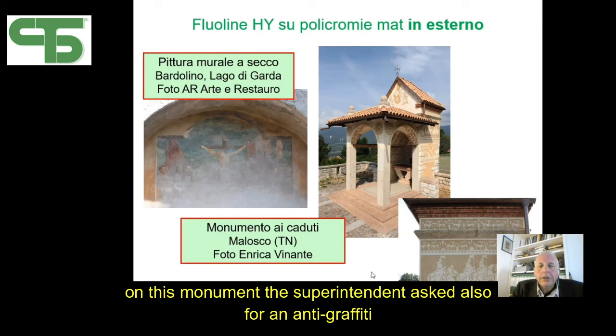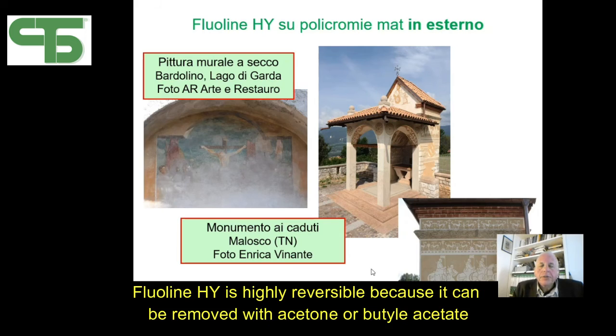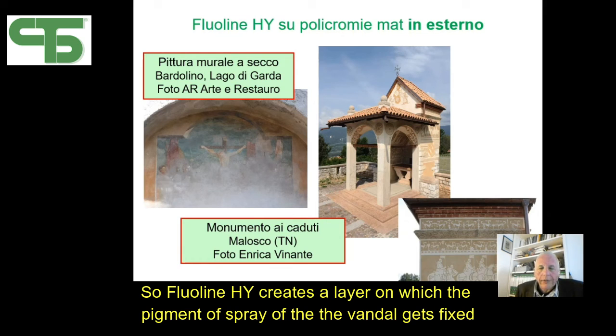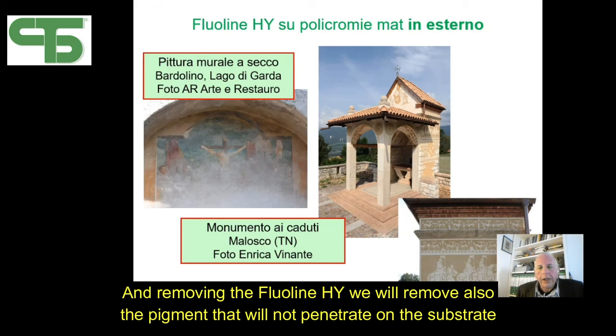On this monument, the superintendent also asked for an anti-graffiti, and Fluoline HY is highly reversible because it can be removed with the help of acetone or butyl acetate. So Fluoline HY creates a layer on which the pigment of the vandal's spray gets fixed. And just by removing the Fluoline HY, we will also remove the pigment, which will not penetrate the substrate.